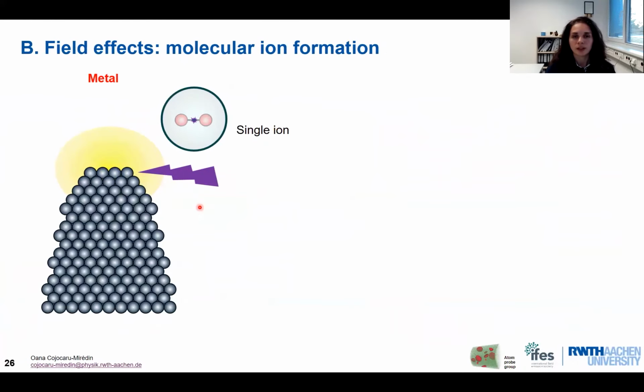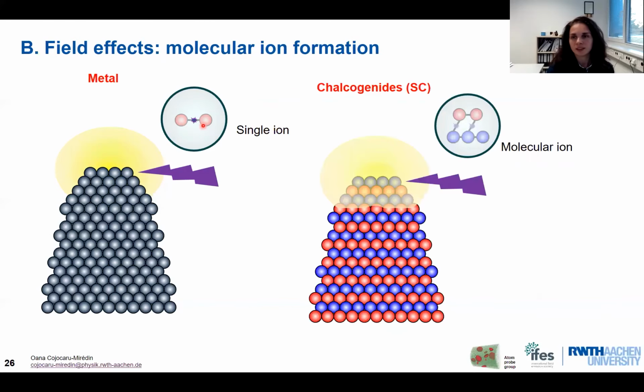So now if I summarize what I have said in terms of field penetration depth and molecular ion formation, we can state that for the metals, we have a very low field penetration depth. And this explains why we have the absence of molecular ions on the mass spectra when we use regular standard modern atom probe tools.